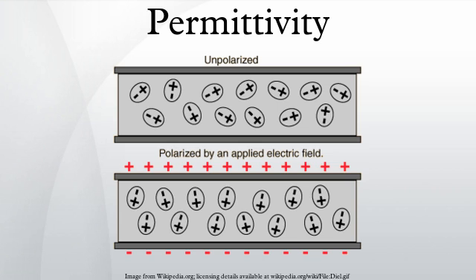The response of a medium to static electric fields is described by the low frequency limit of permittivity, also called the static permittivity epsilon_s. At the high frequency limit, the complex permittivity is commonly referred to as epsilon_infinity. At the plasma frequency and above, dielectrics behave as ideal metals, with electron gas behavior. The static permittivity is a good approximation for alternating fields of low frequencies, and as the frequency increases a measurable phase difference delta emerges between D and E. The frequency at which the phase shift becomes noticeable depends on temperature and the details of the medium. For moderate field strength, D and E remain proportional.